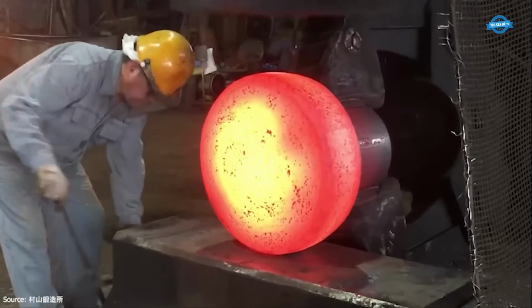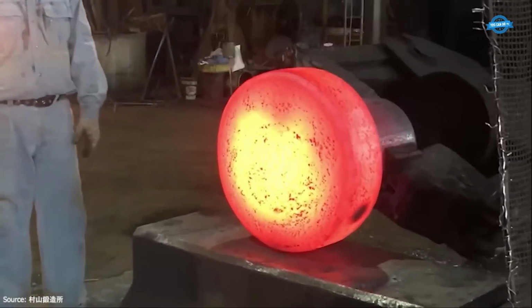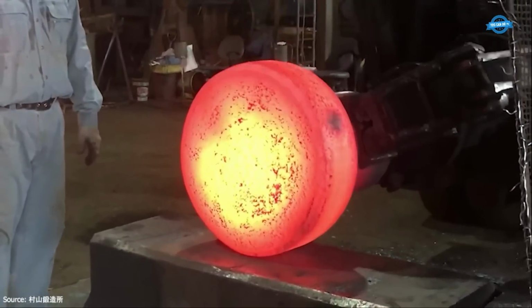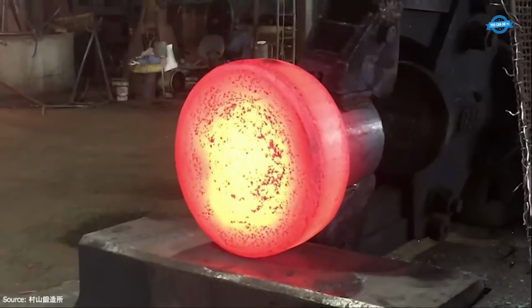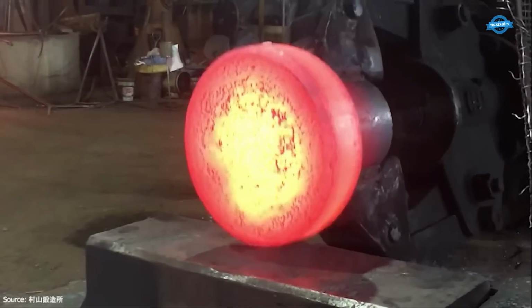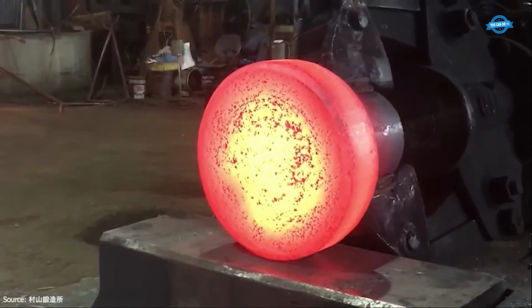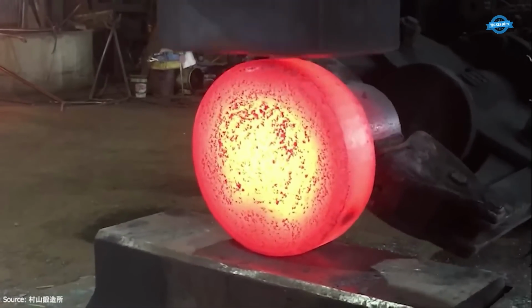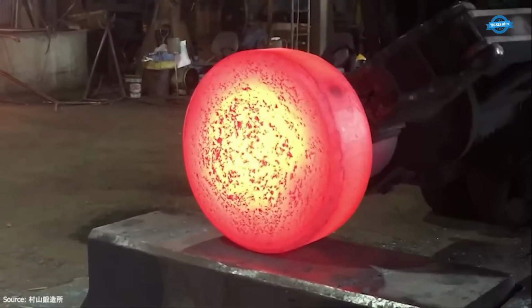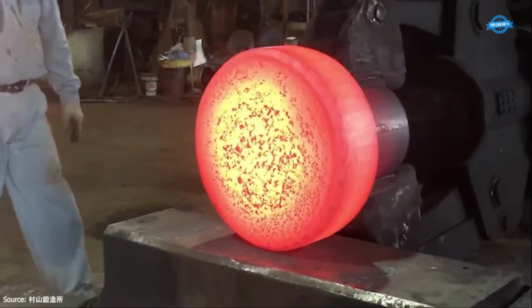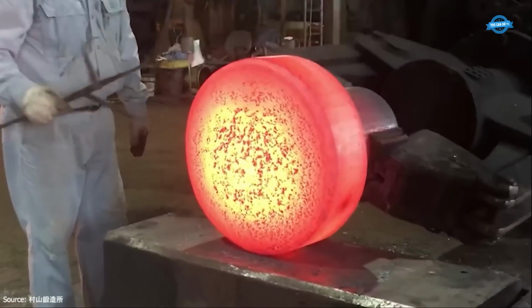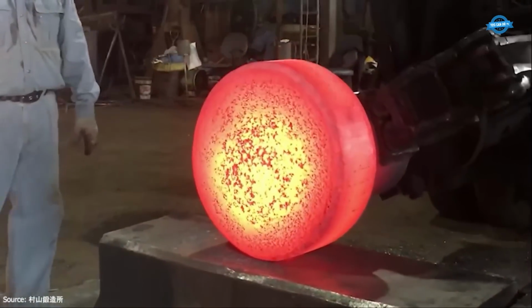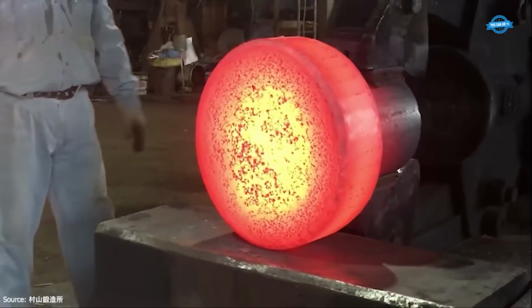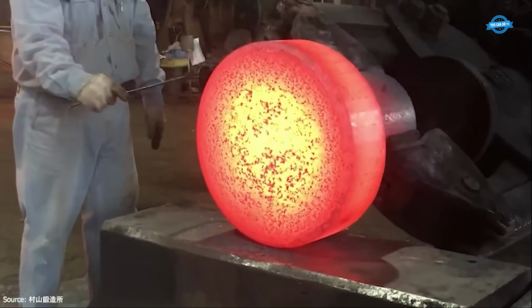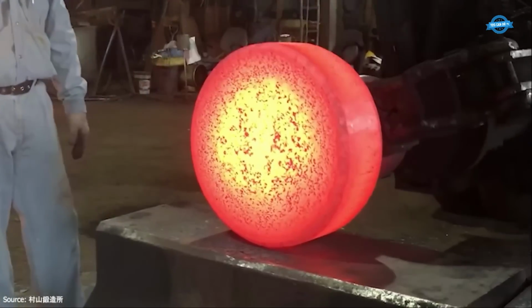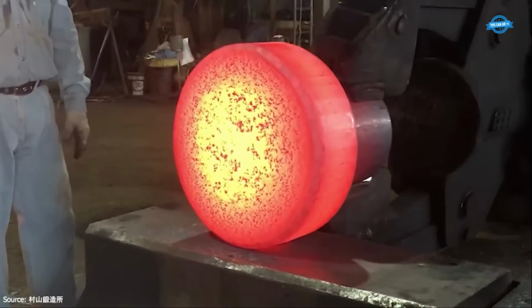The forming process officially begins. The billet is placed on a large open-die hydraulic forging press, typically operating with forces exceeding 2,000 to 5,000 tons, depending on billet size and material. The operator carefully positions the billet under the press and executes controlled deformation strokes. The initial pressing flattens and spreads the billet to establish basic proportions. Skilled rotation and repositioning are essential to ensure even material flow, avoiding weak points or anisotropic grain structures.